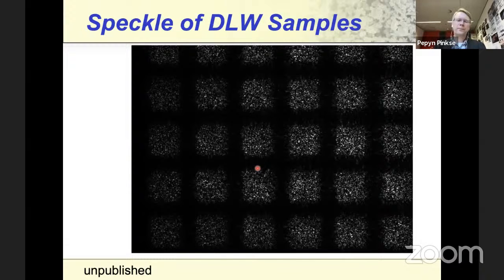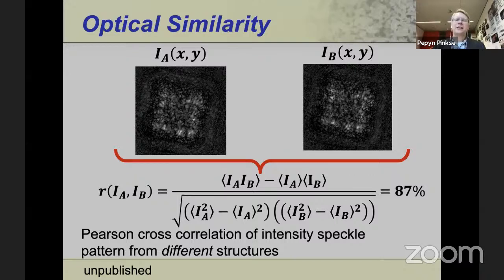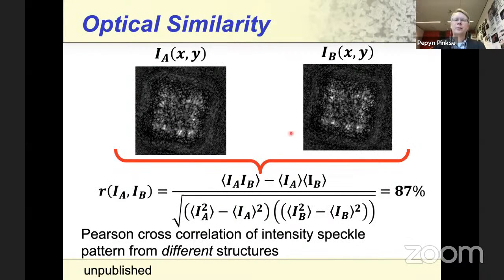However, if you work hard and produce many of these samples, and you control your fabrication process, and you work on the same day on the same sample holder with the same dye, the same laser power, then sometimes you can get samples with the same speckle patterns. So these are two different pictures of two different objects illuminated in the same way, showing speckle patterns which are 87% identical.